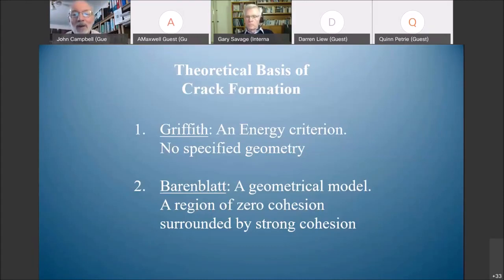Now, when you write out whether this is going to propagate as a crack or whatever it's going to do, interestingly, we come up with the Griffiths model. So these two models actually give the same answer. But this model, where we have a region of our lattice with no cohesion, surrounded by a region of strong cohesion, this is a bifilm. It could not be a better model of a bifilm. And so I was very, very happy to see this, because here a bifilm model by this clever Russian has given us the same mathematical solution to cracks as Griffiths did 100 years before with a rather different energy model.